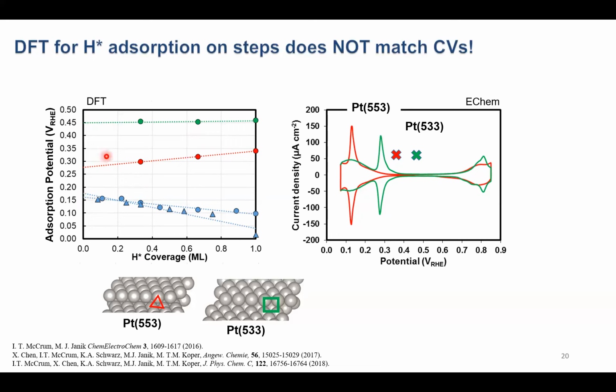So the first thing we can see is that adsorption on the steps is much stronger than on the terraces. We might expect this because the stepped platinum atoms are under-coordinated, so they should bind most adsorbates more strongly. But what's kind of concerning is if we now compare this adsorption potential for hydrogen on the steps to experiment. So here I'm showing again the CVs measured experimentally on platinum 553 and 533 in an acid electrolyte, compared to our DFT predicted adsorption potentials for hydrogen on the steps, shown with these X's here, these crosses. We see that they are far more positive than what's observed experimentally, right? And so I think experimentalists might look at this and say, okay, well, DFT sucks. It's not useful here, right?